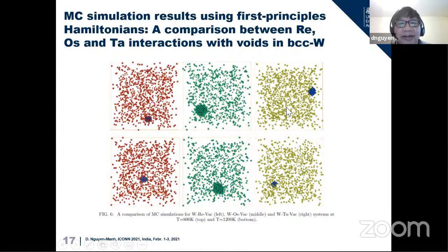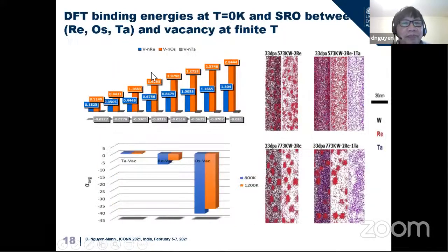And we can understand that very simply from DFT calculation. For example, if we look at the binding energy of a single vacancy with nearest neighbor rhenium, osmium, and tantalum in the BCC lattice, we can see that the binding energy of vacancy with rhenium is positive, meaning that they are attractive, whereas osmium is also positive, but stronger than rhenium.